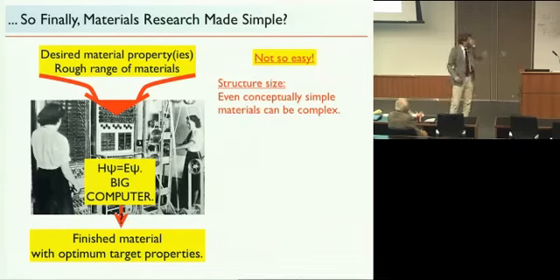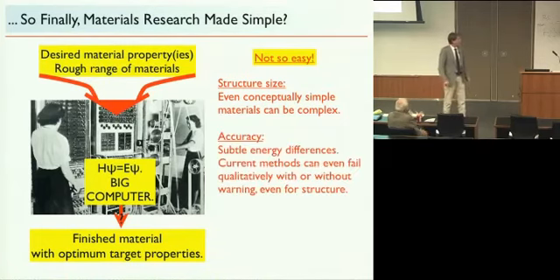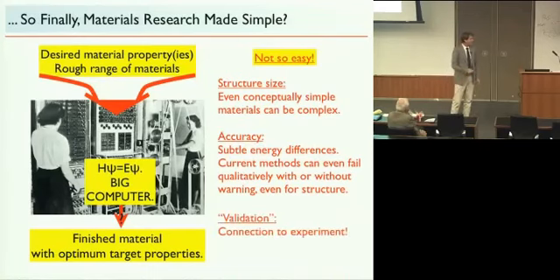First of all, there's the issue of structure size. Even conceptually simple materials like graphene on silicon carbide can have complex structures, so structure space is large. But second, the argument that I just made about minimum energies relies on energy differences, and these can be subtle between different structures. And current methods can fail even qualitatively, with or without warning, for certain of these structures. And that's an ongoing challenge for the community. So we certainly need this third aspect here, which is constant validation of the theories by connecting to experiment as much as we can do.